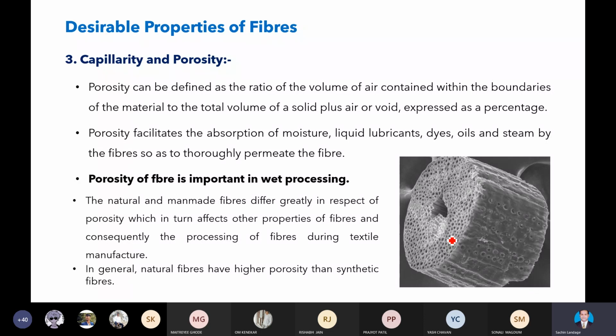When you take 1 kg of wool fiber, dip it in water, remove it and squeeze it, and then check the water content, you will get 1.33 kg, meaning 1 kg of wool fiber and the remaining 33 is water. Now why does it have good water holding capacity? Because of the porous structure. The water will go through these channels, from this end to this end. This is the cross section. Throughout the fiber length, such a porous structure is found.